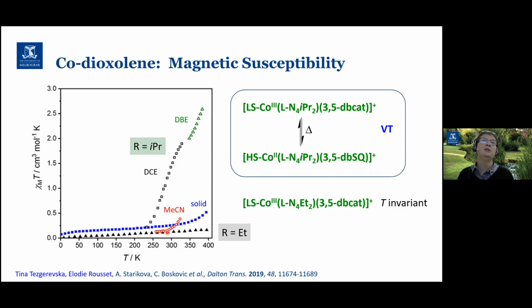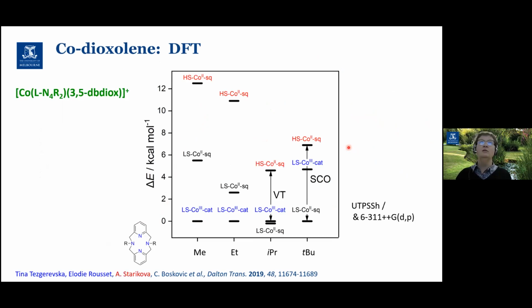And again, when we look at that in solution, so we've got 3 different solvents here, acetonitrile, dichloroethane, dibromoethane, we can actually see chi-T values and chi-T profiles consistent with almost a full VT interconversion, depending on the solvent. So going to the high spin cobalt-2 semiquinone form. So that struck me as being absolutely fascinating, just varying those R groups on the ancillary ligand that you wouldn't really think would have very much to do with VT or spin crossover transitions. You can not only control the charge distribution, but you can control which type of transition that you get.